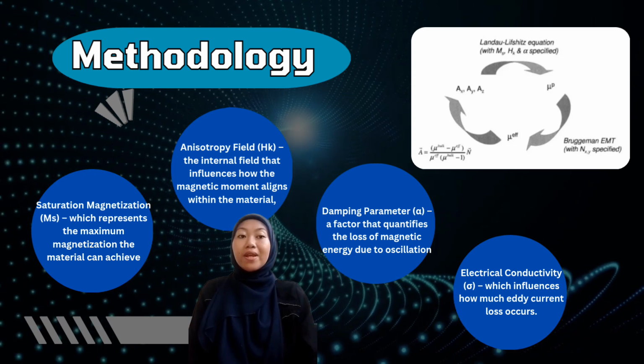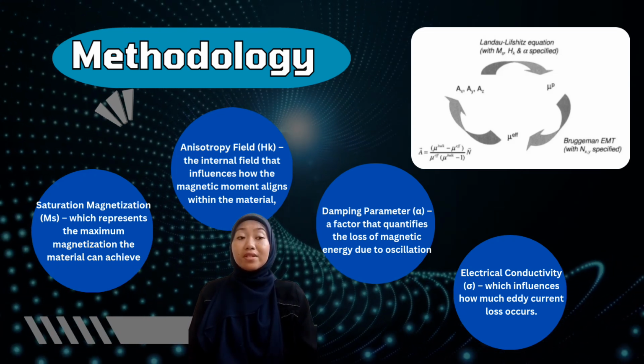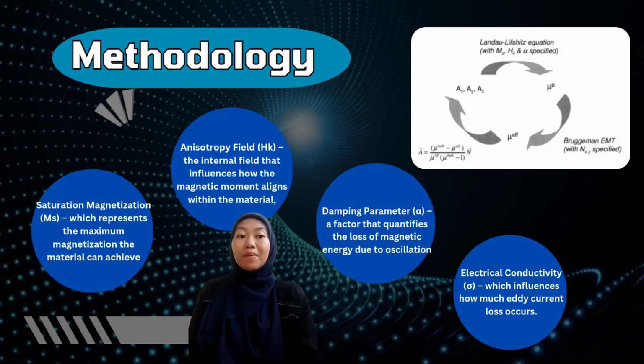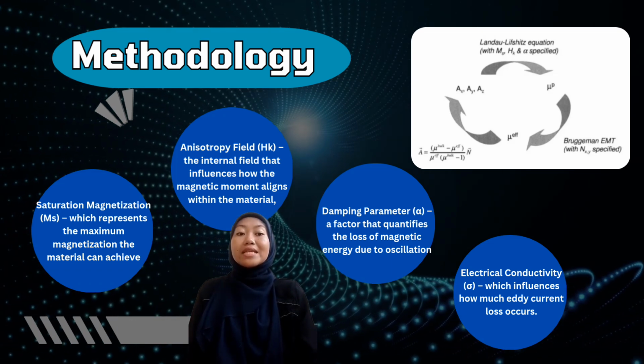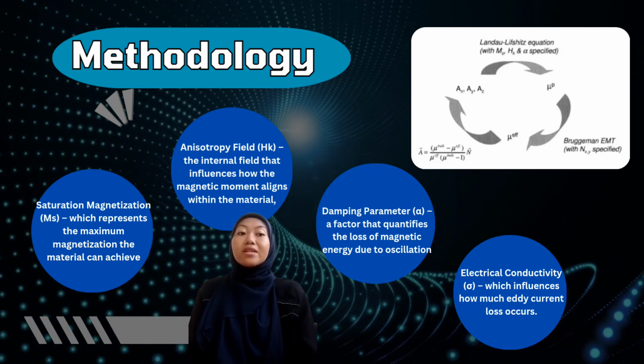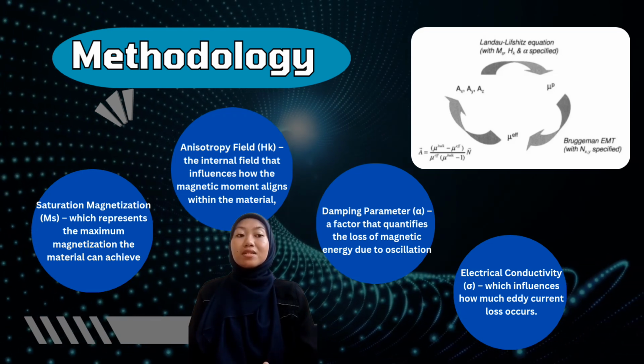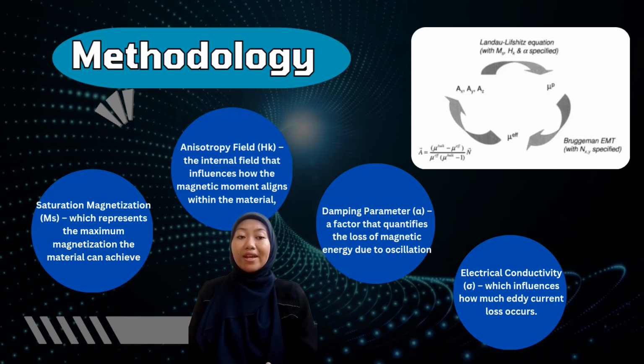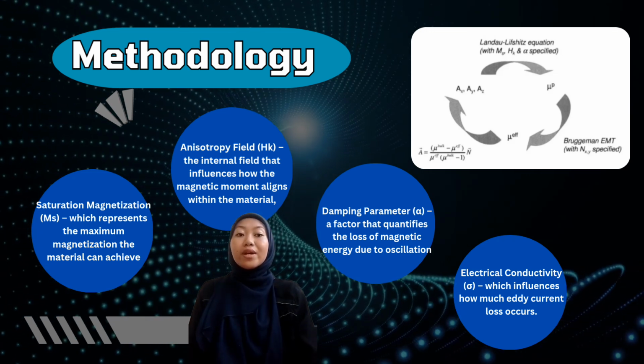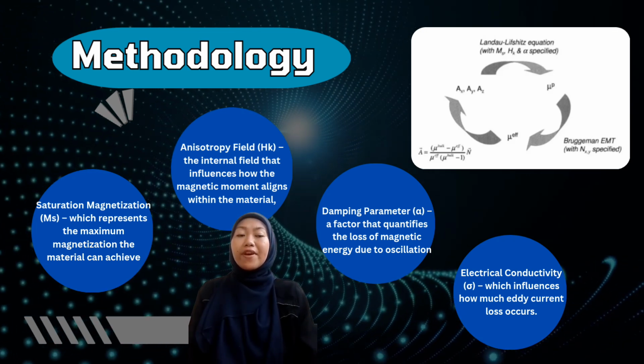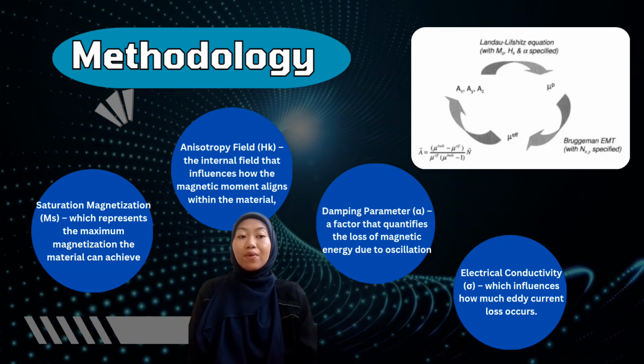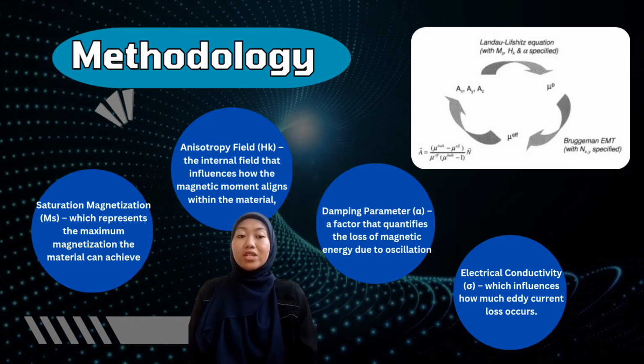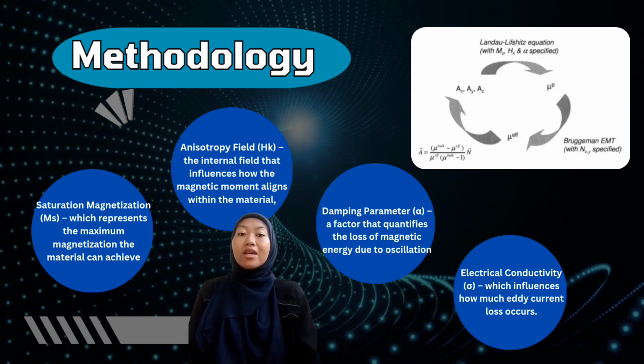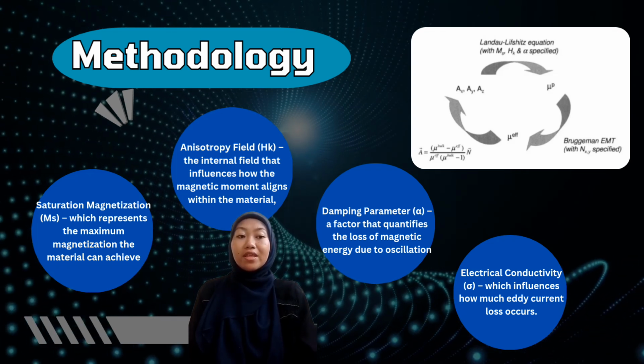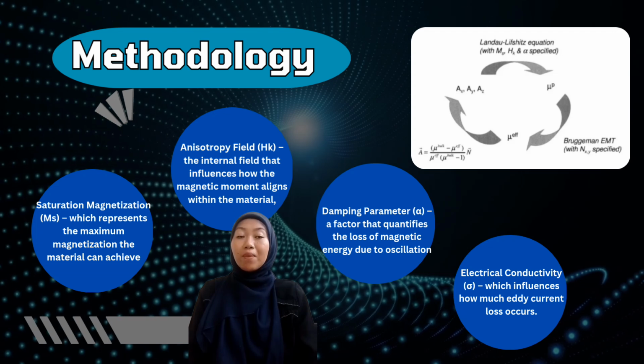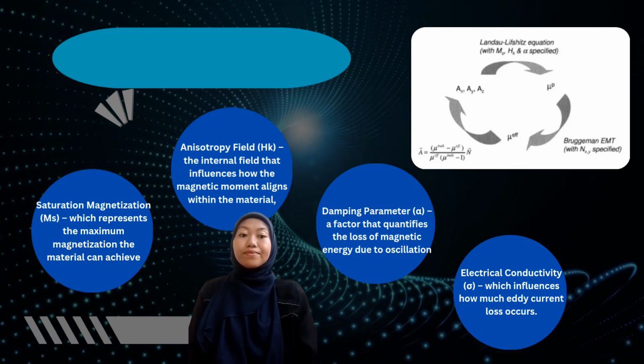Methodology. There are 4 key material parameters. First one is saturation magnetization (MS), which represents the maximum magnetization the material can achieve. Second one is anisotropy field (HK), the internal field that influences how magnetic moments align within the material. The third one is the damping parameter, a factor that quantifies the loss of magnetic energy due to the oscillation. And the last one is electrical conductivity, which influences how much eddy current loss occurs.